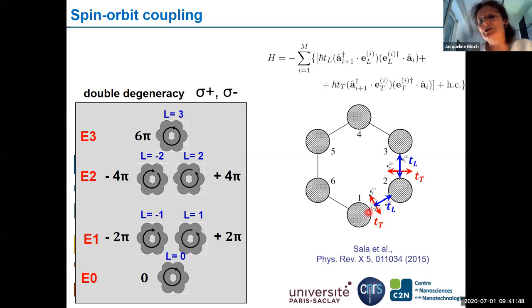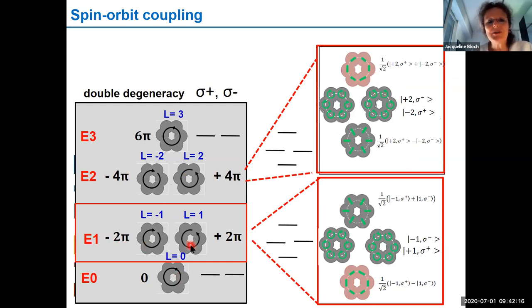So you see that we couple the polarization degree of freedom, which is the spin degree of freedom, if we consider that light has a pseudo-spin, which can be plus one for sigma plus and minus one for sigma minus polarization. So there is a coupling between the spin of the mode and the azimuthal angle, which means the orbital degree of freedom. If you compute this Hamiltonian, you find that these two levels, which are so interesting, acquire a fine structure. And you see that they split into three levels. The lowest one corresponds to a linear superposition of L equal minus one sigma plus and L equal plus one sigma minus. So you see that the degrees of freedom of spin and orbital are now entangled. And this mode corresponds to a linearly polarized mode with an azimuthal polarization. The upper one is also an entangled state, but with a different linear combination. And there the mode is radially linearly polarized.